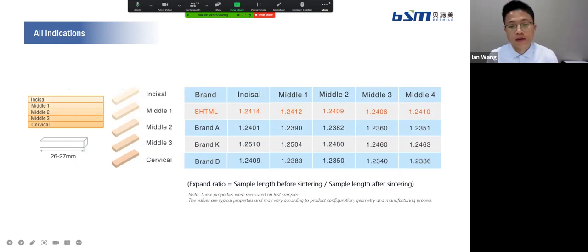And when we use traditional multilayer for long bridges, we may find it has a bad fit. This is because of the uneven particle size distribution, as I showed in the earlier images. It will get an uneven deformation during sintering, so after sintering, we will find the restoration has a bad fit. And how about the newly upgraded SHTML?